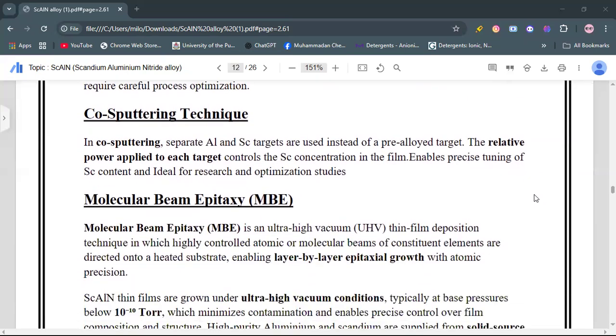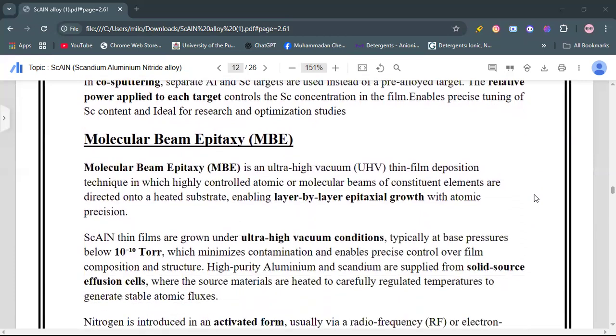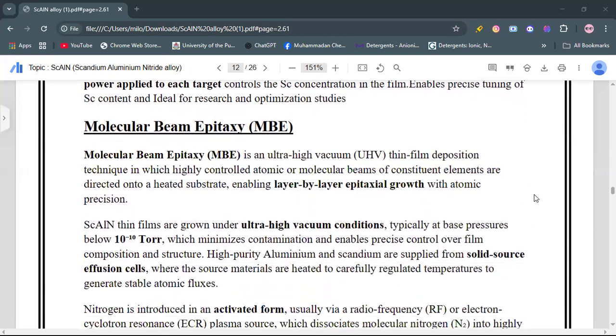The next is molecular beam epitaxy. It is an ultra-high vacuum thin film deposition technique in which highly controlled atomic or molecular beams of constituent elements are directed onto a heated substrate, enabling layer-by-layer epitaxial growth with atomic precision. Scandium aluminum nitride thin films are grown under ultra-high vacuum conditions, typically at base pressures below 10^-10 torr, which minimizes contamination and enables precise control over film composition and structure.